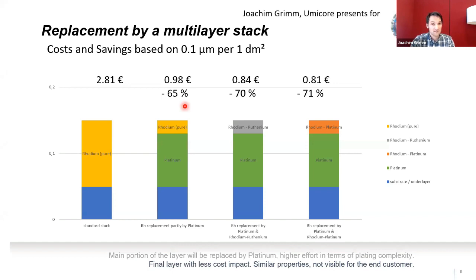And for your client, the quality is still the same. There is the abrasive resistance, there's the corrosion resistance, and it's still the white, shiny rhodium plating. But about saving, you can get additional one step. The systems I described before can be put instead of the pure rhodium on top, and underneath you still have the platinum. So if you go instead for the pure rhodium now for the platinum as an intermediate layer, and then the rhodium-ruthenium on top, you will have a saving of 70% compared to the pure rhodium stack, and it comes down to a price of 84 euro cents.